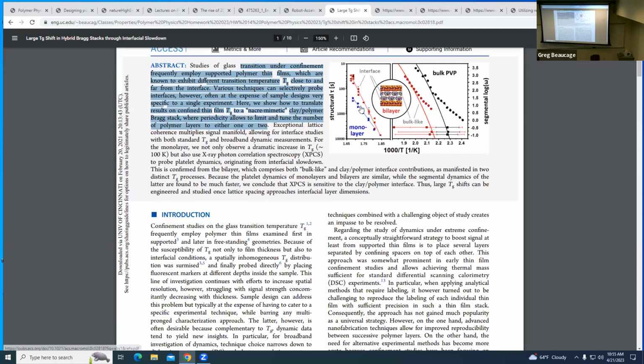So they're looking at that kind of material with X-ray photon correlation spectroscopy. So they can do an X-ray pattern on this, then you can get the stacking period at high Qs, like 0.1, maybe 0.4, there'll be a peak associated with those stacking. So it's not a diffraction peak exactly because it's water disorder. And as you exfoliate it, that peak gets to larger sizes, so it moves to lower Q, and it also disappears at some point. So it's a sharper peak, and it becomes less sharp as you exfoliate. So you can watch the exfoliation process with X-rays.